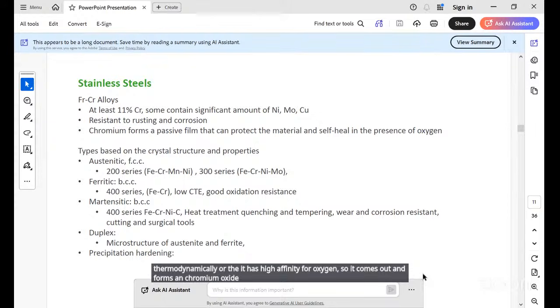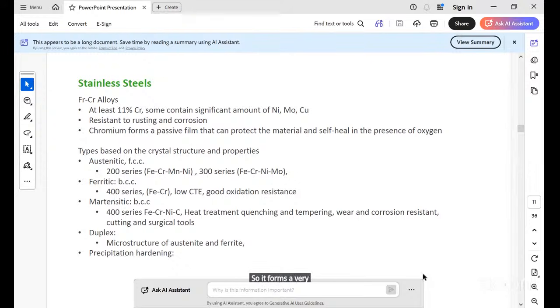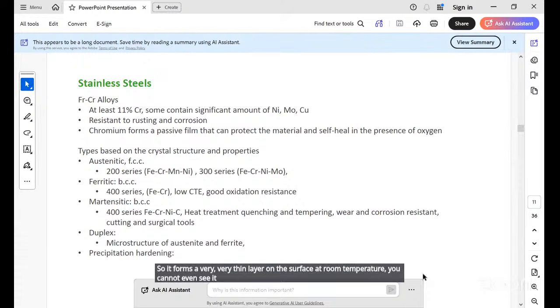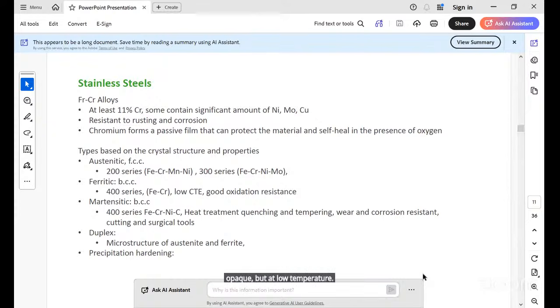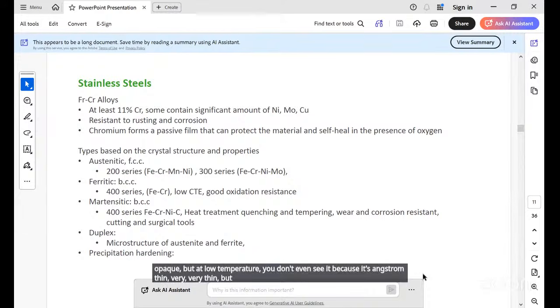And we like chromium oxide because it grows very slowly. Iron oxide grows very fast. So it forms a very, very thin layer on the surface. At room temperature, you cannot even see it. The material looks shiny and everything, and you cannot see chromium oxide. At high temperature, you can see chromium oxide layer, which is opaque. But at low temperature, you don't even see it because it's angstrom thin. Very, very thin. But this is the one which provides the passivation for corrosion resistance.